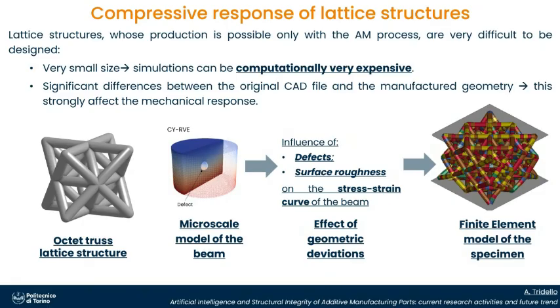We developed a multi-scale approach. Our objective is to define a simplified methodology. So this small portion of the beam contains a defect and a surface roughness. We would like to model the effect of defect and surface roughness on the stress strain curves. And then we put these stress strain curves into a specimen, which I have also tested experimentally, to verify the influence of these two deviations from the original CAD file.